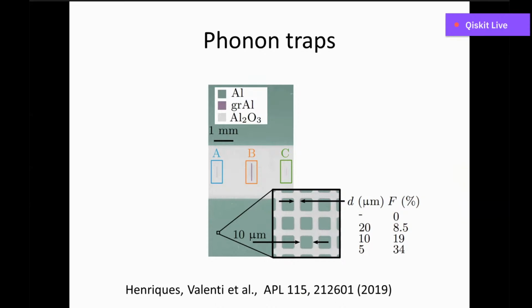Francesco, that's very interesting. How do you choose the size for your initial approach? Why not have one big one? Why 10 microns, not 100 microns versus 1 micron? This was a small enough feature size that allowed any resonant phenomena of the islands to stay well outside our band and to ensure no flux trapping in our lower gap material, while being easy to fabricate with our technology.